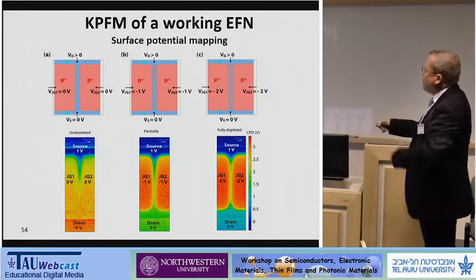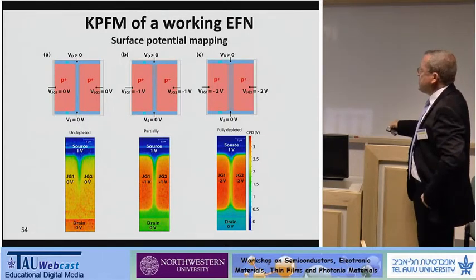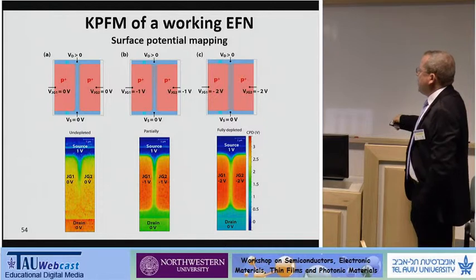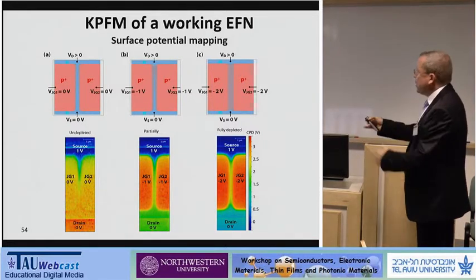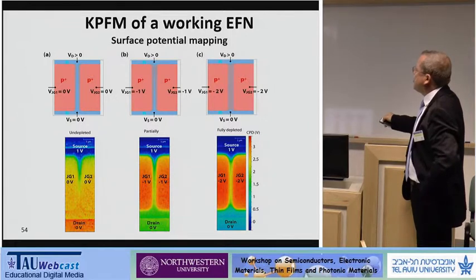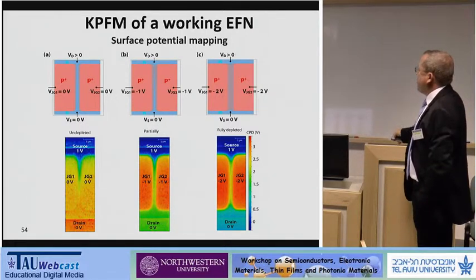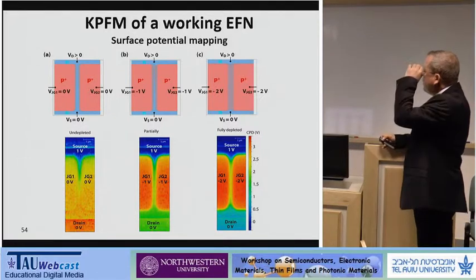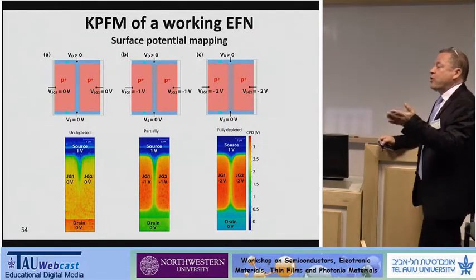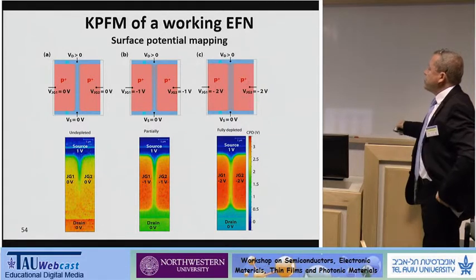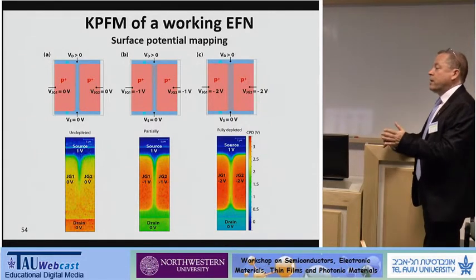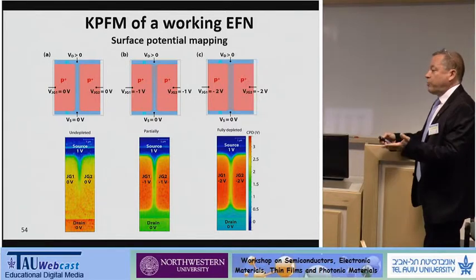When we have no bias applied to the side gate, this is a large nanowire. When we have a slightly negative voltage, the nanowire is decreased. You see the depletion regions extend on both sides. And when we have a really closed channel, a pinch-off, we can really see it nicely with KPFM. So this is a big advantage. You have to remember that I don't measure the carrier distribution here. I want to emphasize that I measure the potential profile.